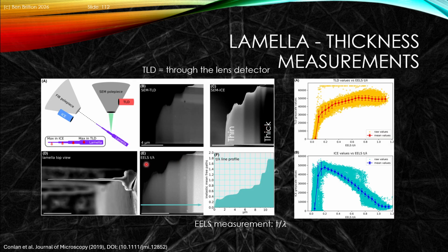And then they've linked this to a t over lambda EELS measurement, which is one of the classical methods for thickness. This enables you to extract the inelastic mean free path from the t over lambda. And what you can see is that you can get some nice grayscale values matching with the thickness from t over lambda. And if you calibrate this well, you could then use this as a method to do an EELS-free calibration of the thickness of your foil, which can be particularly powerful as you want to increase the throughput of your analysis method.